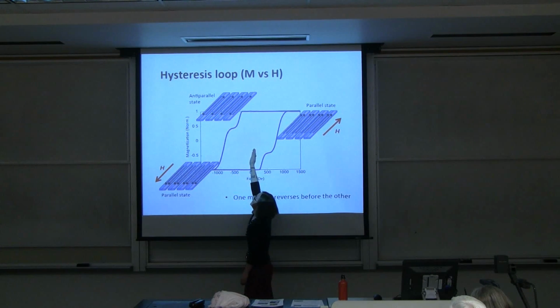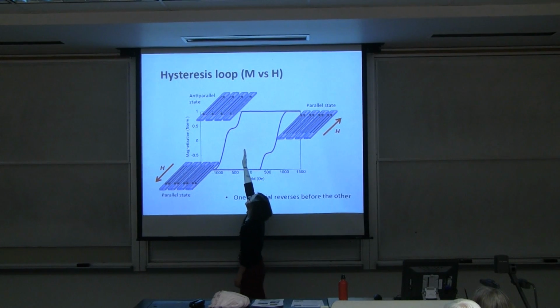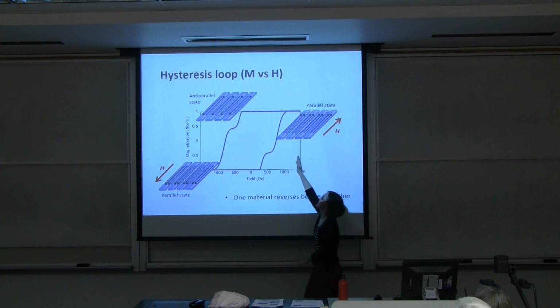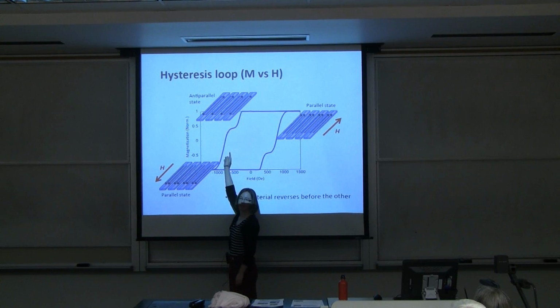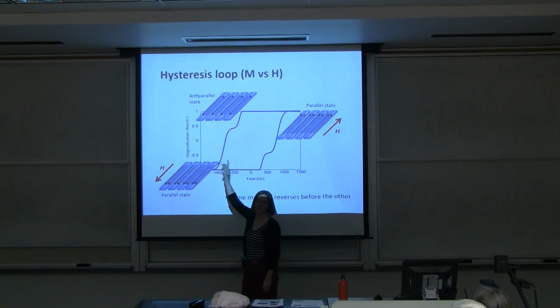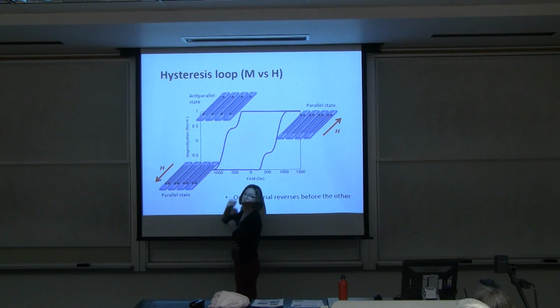Now if we go back and we reverse the magnetic field, what you can see is it stays magnetised in one direction for a while, and then one of the stripes flips. So just the nickel ion, it's not really clear on that diagram, but just the nickel ion flips and the cobalt ion stays magnetised in the other direction. So this is what we call the anti-parallel state. One of the stripes is parallel to the magnetic field, and the other stripe is still anti-parallel to the magnetic field. So that's this little plateau region in here.